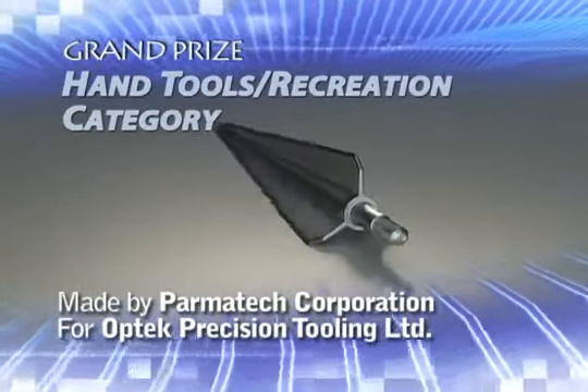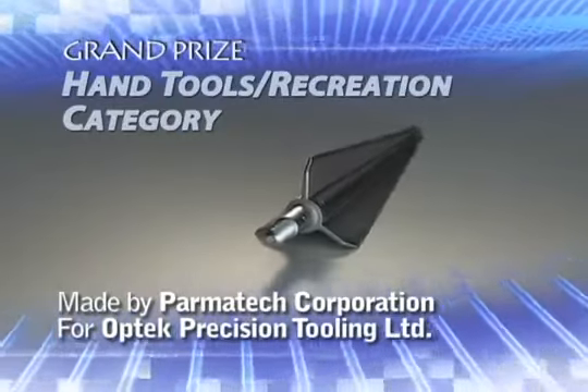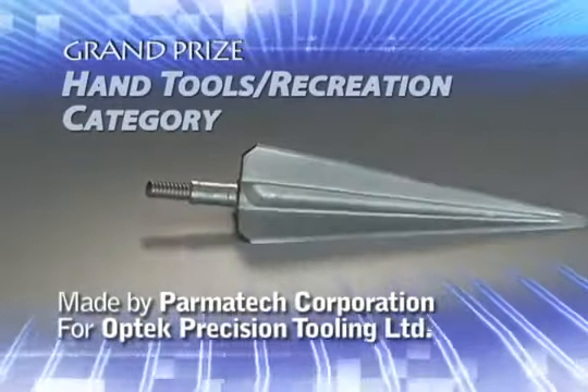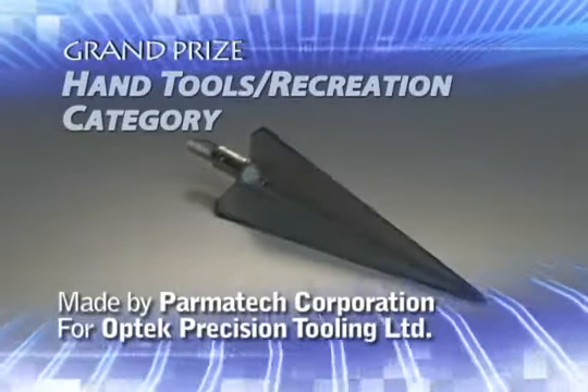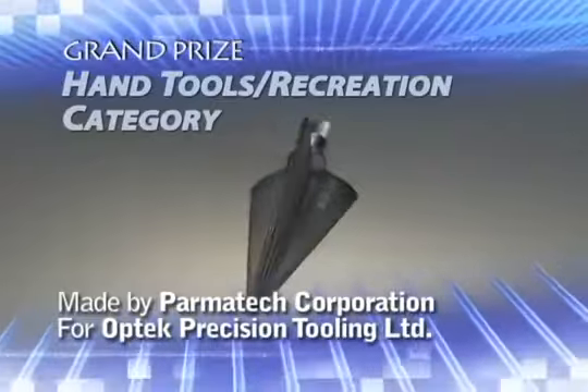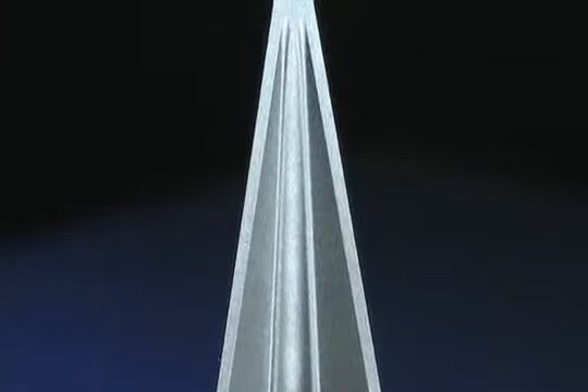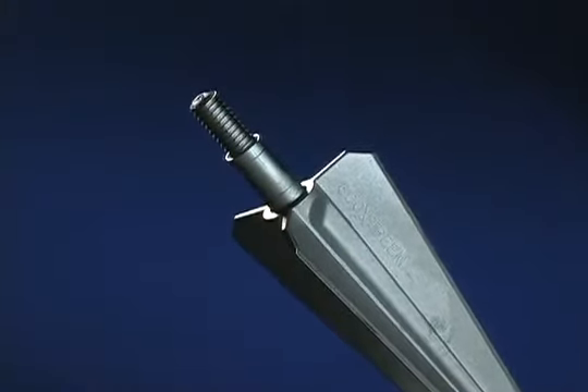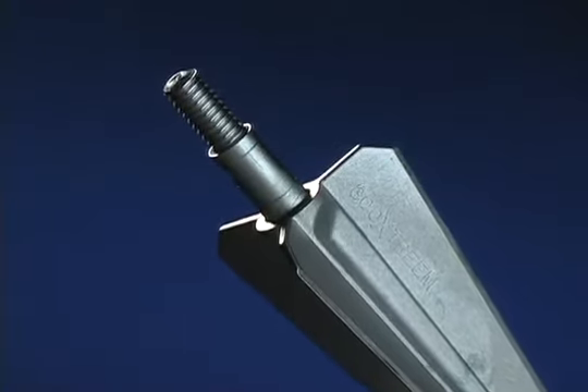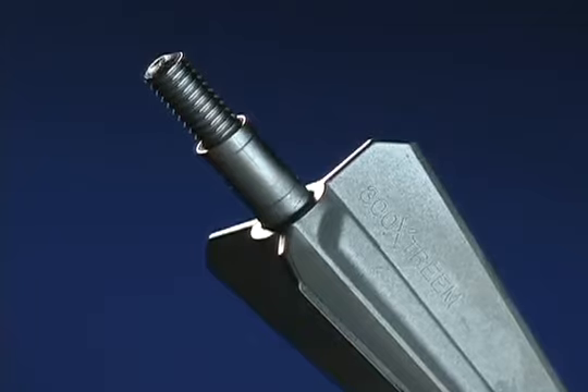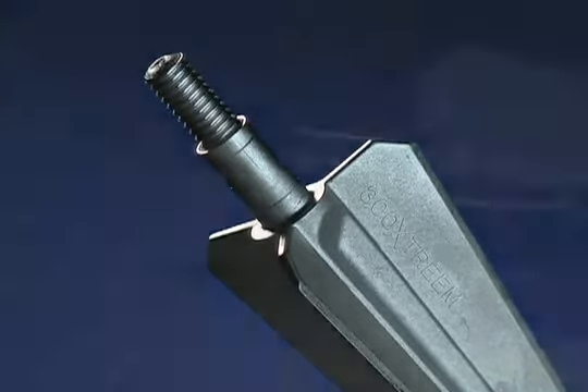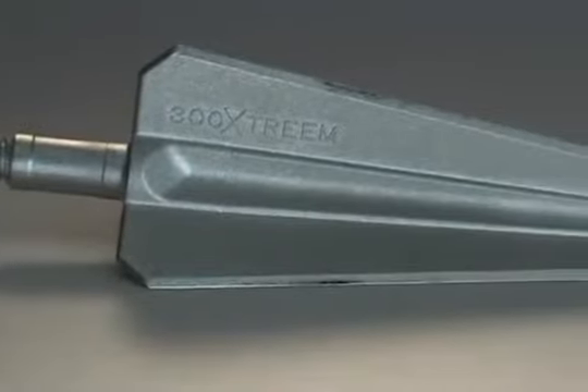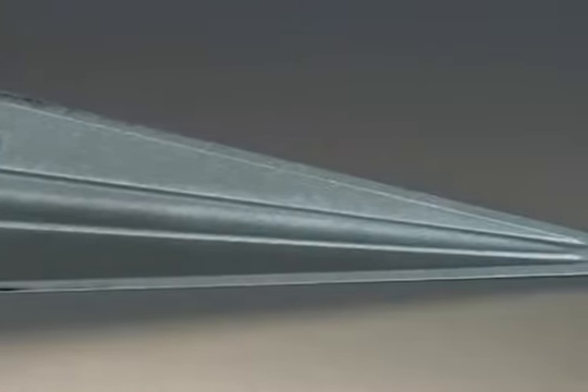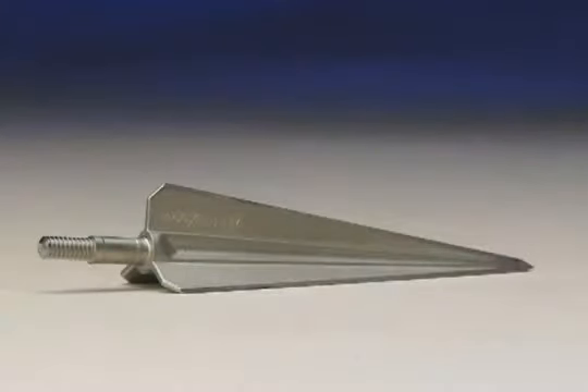Parmatech Corporation has earned the grand prize in the hand tools recreation category for a large game 420 stainless steel hunting arrow 300 Extreme Broadhead made for Optech Precision Tooling Limited. Fabricated by the MIM process, the thin blade features a critical straightness necessary for accuracy, and the external thread is molded in the design. The part is formed to a final density of 7.7 grams per cubic centimeter and has a 48 to 52 HRC hardness range. Going the metal injection molding route saved 50% of the cost of machining the broadhead from stainless steel bar. The customer sharpens the arrowhead edge, the only secondary operation performed.